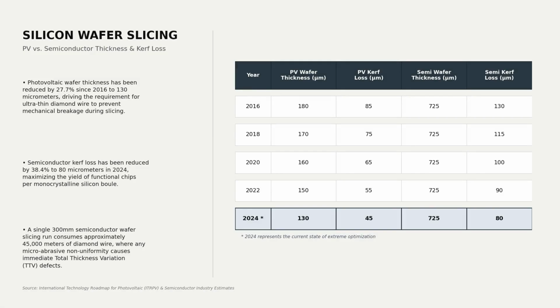Minimizing kerf loss is the primary driver of wafer manufacturing economics. Photovoltaic wafer thickness has fallen 27.7% to 130 micrometers. This reduction requires thinner wires to prevent mechanical breakage during high-speed slicing. In semiconductor manufacturing, reducing kerf loss to 80 micrometers maximizes the yield of functional chips per silicon boule.